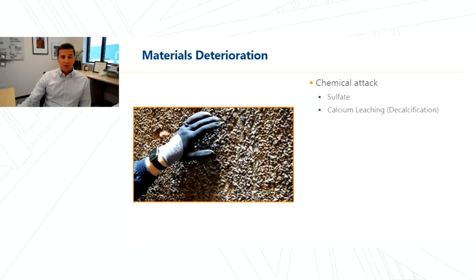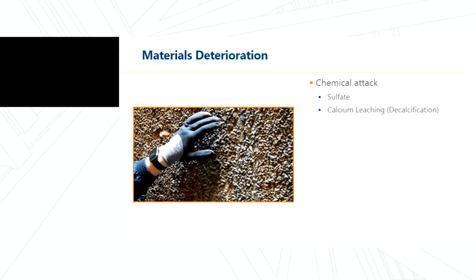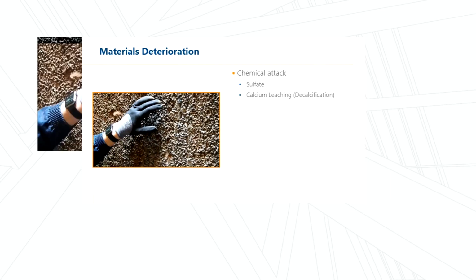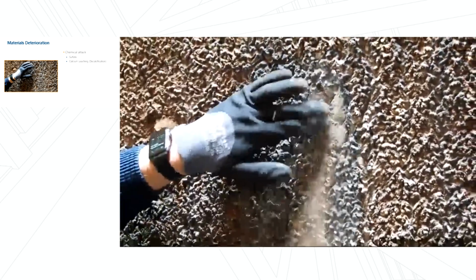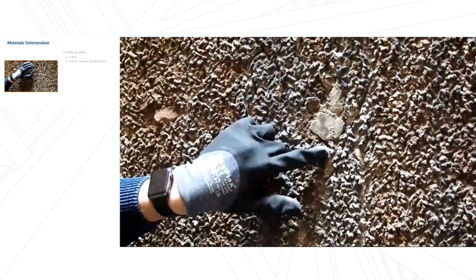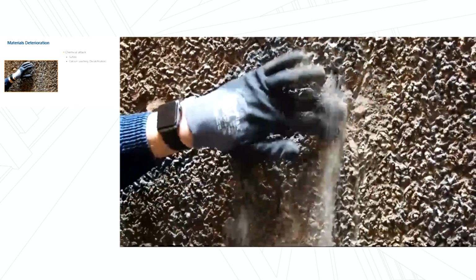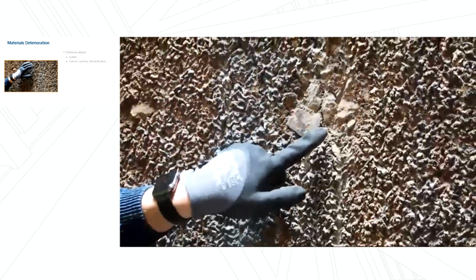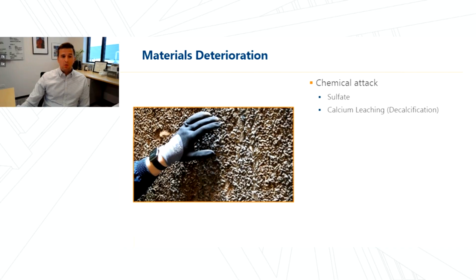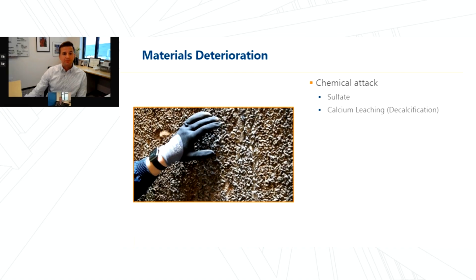Another form of chemical attack is calcium leaching or decalcification. This is a specific form of chemical attack caused by exposure to soft water or acidic conditions, that is, a pH of less than 7. In this situation, it can dissolve calcium-containing hardened phases of concrete, and this results in a loss of strength and stiffness. So whether we're looking at chemical attack or corrosion, there are various options of prevention or repair depending on the nature and severity of the deterioration.